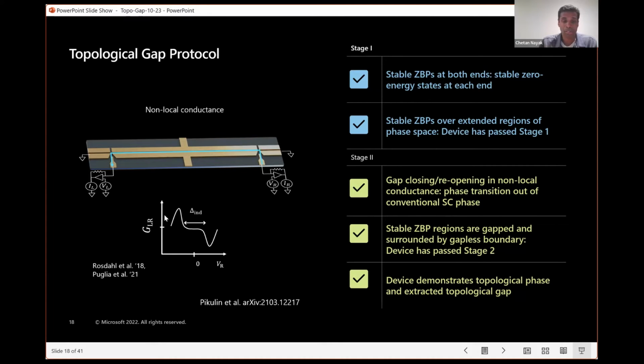The non-local conductance is the derivative, say, of I left with respect to V right. The non-local conductance vanishes at energies below the induced gap, below the gap that's induced in the semiconductor. Because below that gap, you simply can't put any charge in because the system doesn't have any states there. So it's 0 here. And at bias voltages larger than the aluminum gap, it's 0 because you can put charge in, there are states there. But they go straight into the aluminum and the aluminum is grounded, so that charge goes to ground. There's no reason for it to come over here. It'll go straight to ground, take the easiest path.